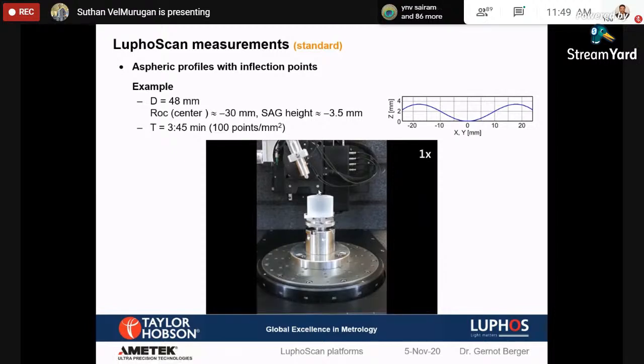It's a tricky profile, so it rotates very slowly, and the rotation of the probe is also very small, and it is a high accuracy part. So we rotated the spindle and rotated the probe at very slow speed. But it takes almost 3.45 minutes to cover the entire part. Still, 3.4 minutes to measure the entire 3D surface is not a big time. It's still very fast. That is to explain to you, so I just ran the video faster.